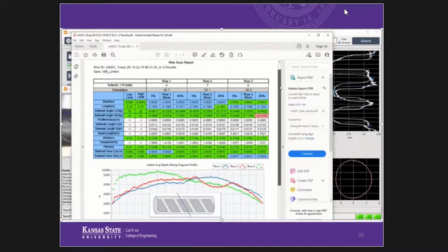So these 3 are the profiles along an indent, what we call kind of generically the north-south direction. If you think of the longitudinal length of the wire as east-west, these would be the average profile from each row of indents. And you can see a couple things right here where the red dips down. If we looked at that wire, it would tend to have a flat spot that was rolled in. Okay, it's not perfectly round. There's a flat spot. So when we measure that indent, it actually comes down because the top portion of the non-indented region has dropped down a little bit.